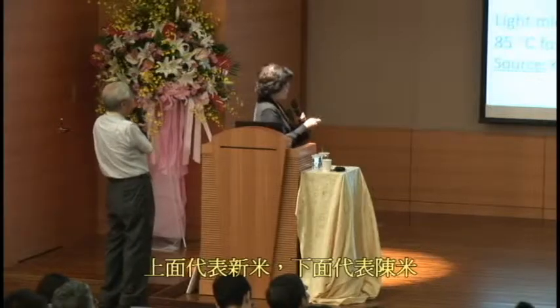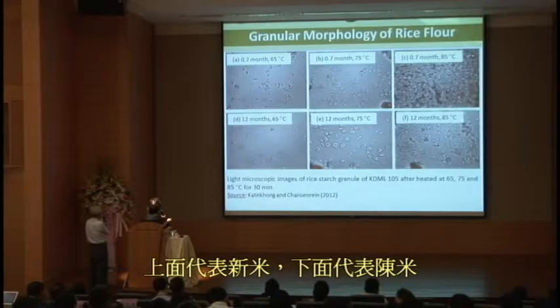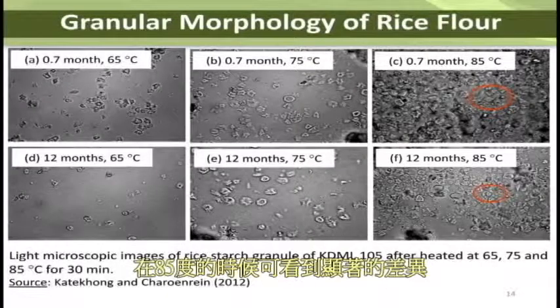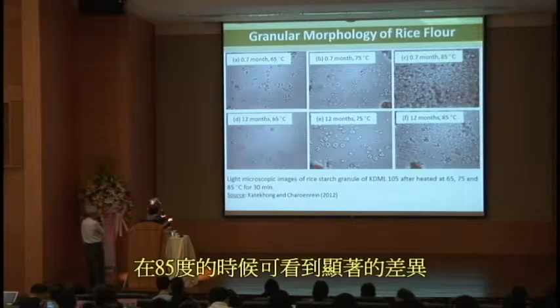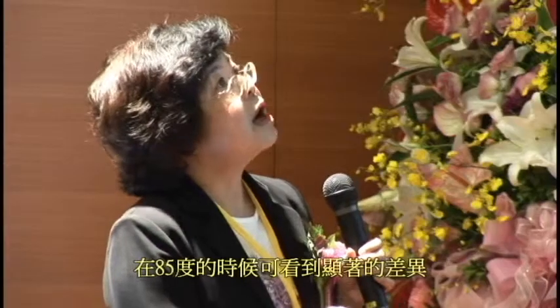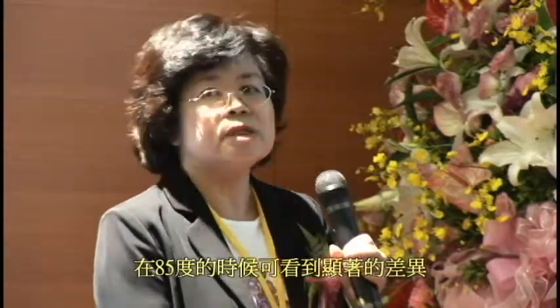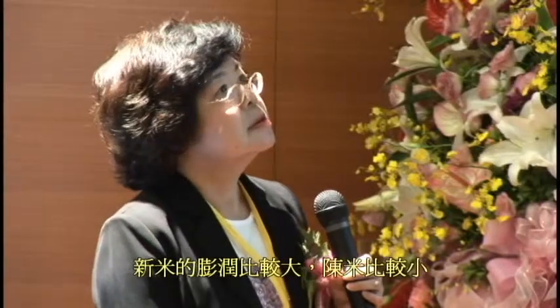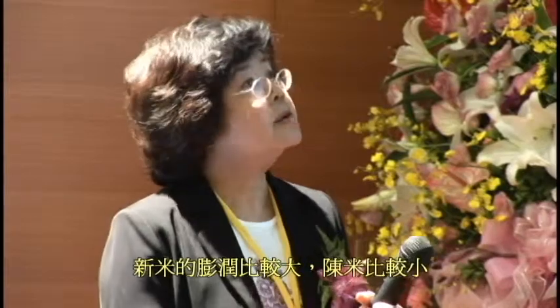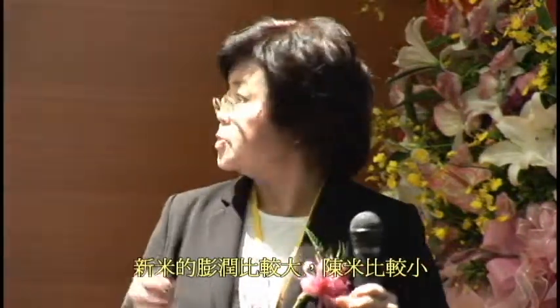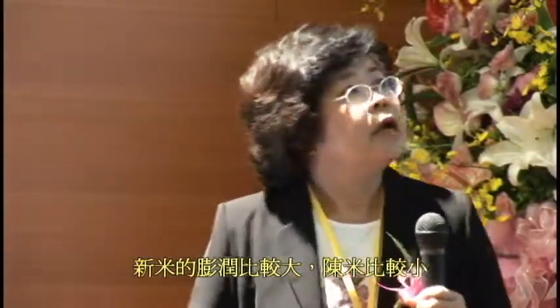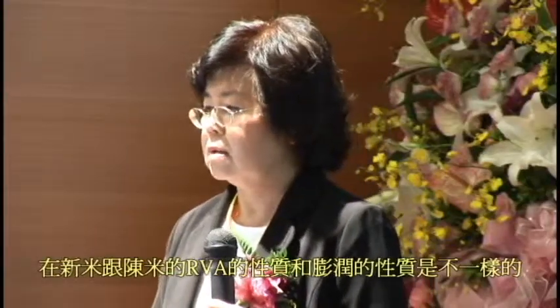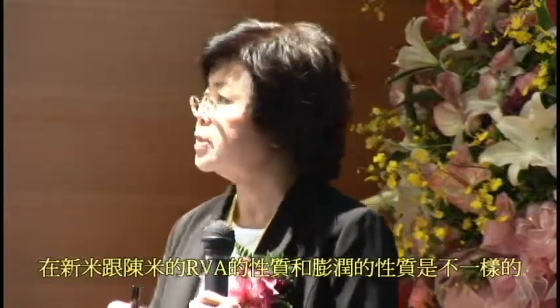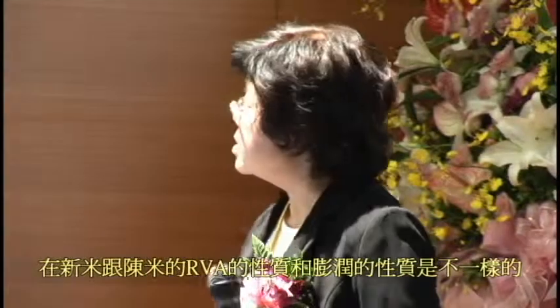And if we look at the light microscope, the top one is the new rice heated at 65, 75 and 85 degrees Celsius for 30 minutes with stirring. And this is the aged rice, the same temperature, same time. You can see that for the new rice, there is a lot of swelling compared to the aged rice. The swelling is less. We would like to propose a mechanism to help explain the results of both the pasting property, swelling, and those pictures from the light microscope.